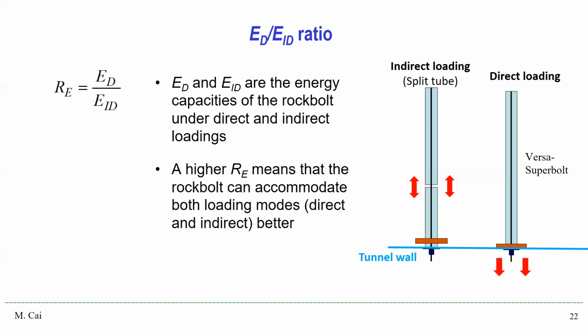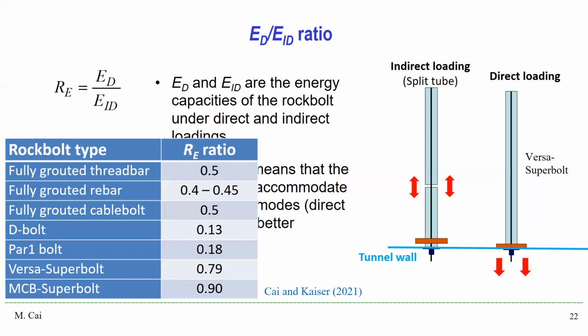Based on the data we collected, we presented some RE numbers in this table. You can see that for fully grouted thread bar, the RE ratio is about 0.5. For fully grouted rebar, about 0.4 to 0.45. For some steel stretching bolts, the RE ratio is a little bit low. And for the hybrid bolt, this RE ratio can be in the range of 0.7 to 0.9. So this is an important parameter to consider when you have to do the rock bolt selection.